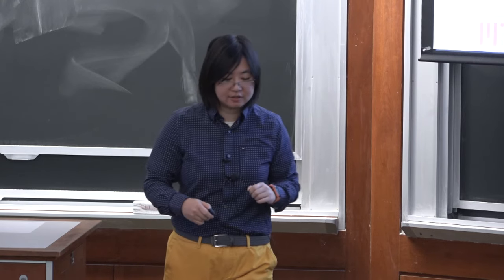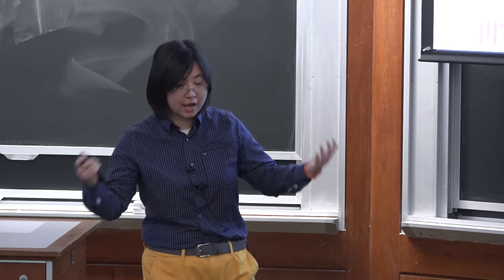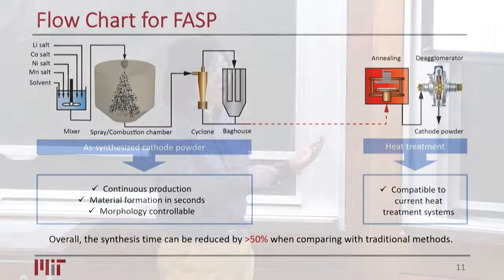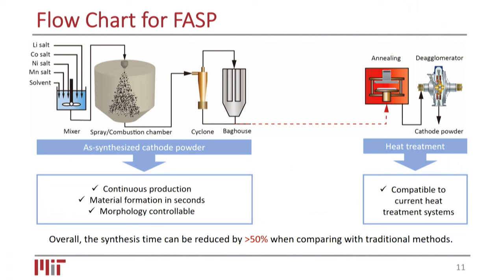This is the flow chart that we envision if we were able to scale up the lab scale FASP process, flame-assisted spray pyrolysis, into an industrial scale. You can directly see that compared to co-precipitation, we have a significantly smaller size and simpler geometry and orientation, et cetera. We can harvest continuous production as well as atomic level mixing in the solution and high throughput manufacturing to get the materials. By connecting things here rather than putting the lithiation into a separate step, we can already reduce the synthesis time by 50%.